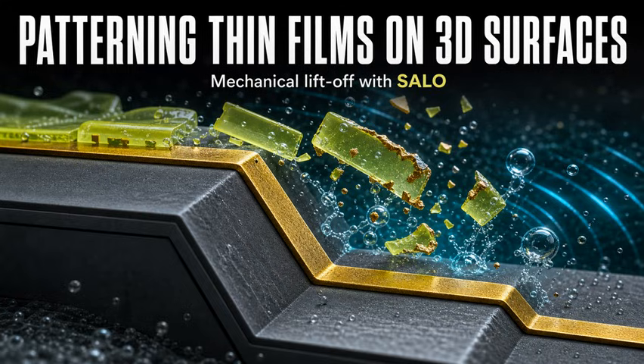Okay, here's where it gets really interesting. Because even if we can cleanly snap this mask off, standard 2PP has a diffraction-limited resolution around, what, 200 nanometers? Yeah, roughly 200. But this paper is claiming sub-30 nanometer features. How are they breaking the physics of the laser? Well, they aren't breaking physics, they're just using a brilliant processing trick. Before they coat the structure with the thin film, they expose the 2PP printed scaffold to an isotropic oxygen plasma. Wait, and that physically shrinks it? Yeah, it physically shrinks the polymer scaffold. So by shrinking the mask first, they successfully yielded patterned metal features as small as 27 nanometers. So the oxygen plasma basically acts as a chemical shrink ray for the mask, cheating the diffraction limits entirely. That's exactly what it does.